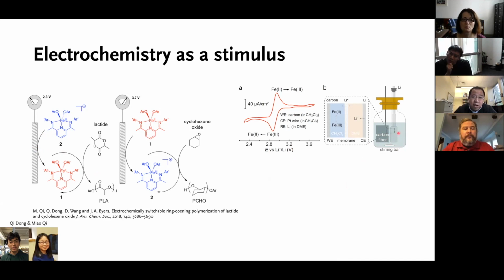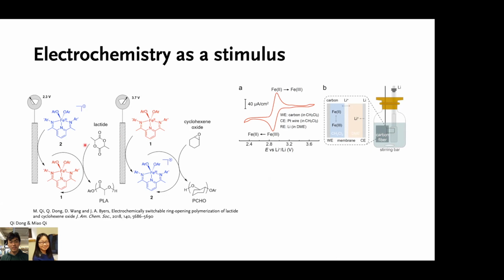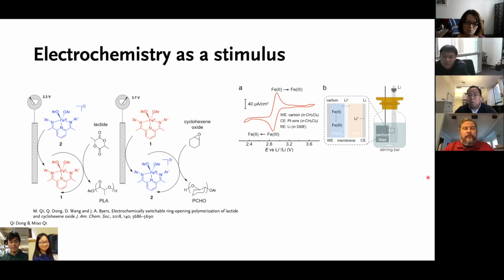Also, they paid a great deal of attention to the counter electrode. When iron here is reduced, something else has to be oxidized. If you don't control it, you're likely going to oxidize either your solvent or, worse still, the recently reduced complex, right? You don't want that. So this is where our experience working with lithium batteries comes in handy. What Qi designed was to use a membrane to separate the rest of the cell and use lithium. We paid attention to lithium not only because we were familiar with how to work with it under electrochemical conditions, but also because Jeff's team has shown that lithium ion in the solution shows very little interference with the polymerization reaction.